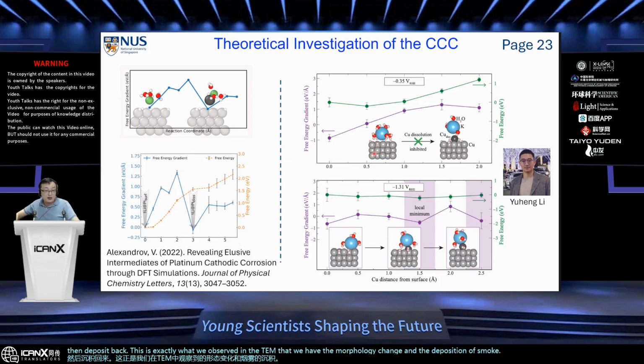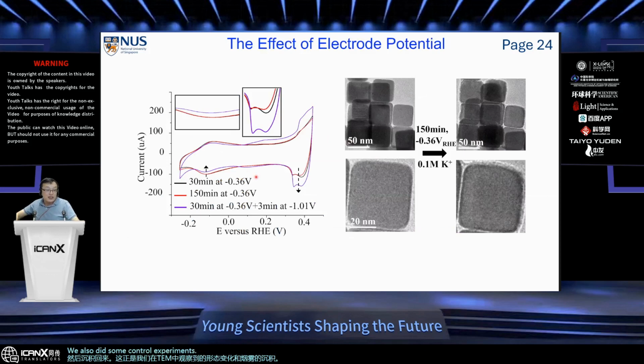We also did some control experiments. One of the characteristics of cathodic corrosion is that, first, you have to have alkali metal cations. Secondly, you have to have a negative enough potential. So in this case, if we control the potential to be only -0.36 volt instead of -1 volt, then we see much less change in the CV as well as in the TEM, even though we deliberately prolong the reaction to 150 minutes. And if we only apply a 3 minute reaction at -1 volt, you will see the big change again, as shown in this purple curve.